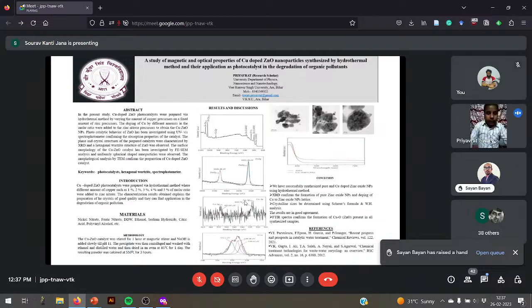Sir, the presence of water hyacinth plant extract in the preparation of Cu-ZnO enhances the porosity and visible light absorption. As a result, the photocatalytic activity of ZnO could be enhanced. Moreover, the impurity level resulting from Cu doping promotes a synergistic effect by suppressing the charge carrier recombination rate and shifting the conduction band to a lower energy level for the overall enhancement of photocatalytic degradation by the Cu-ZnO nanoparticles.